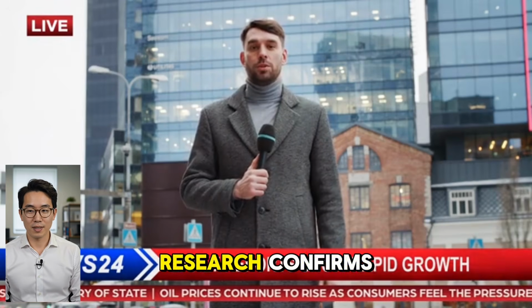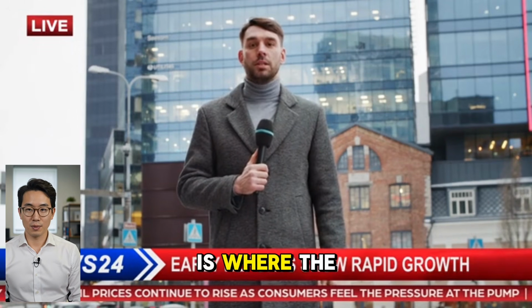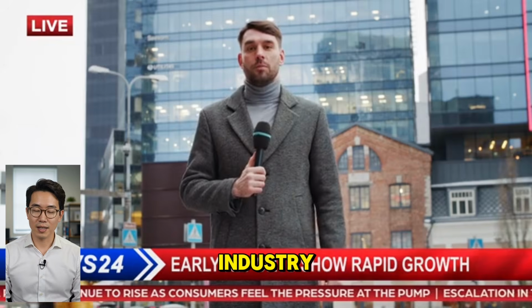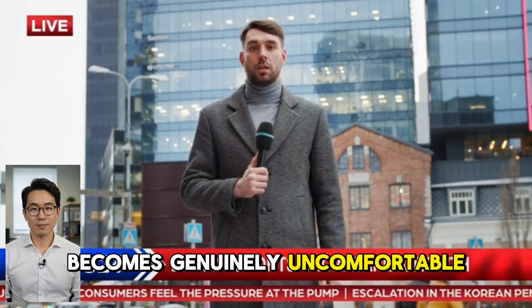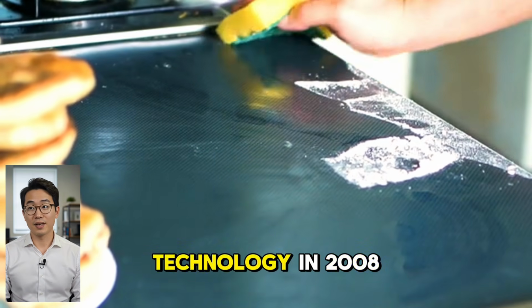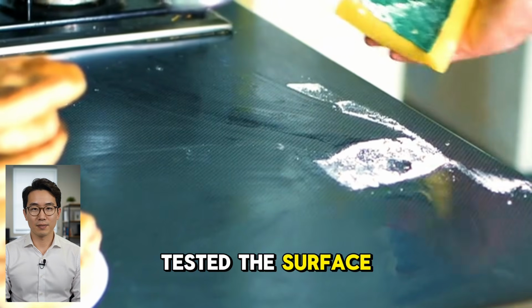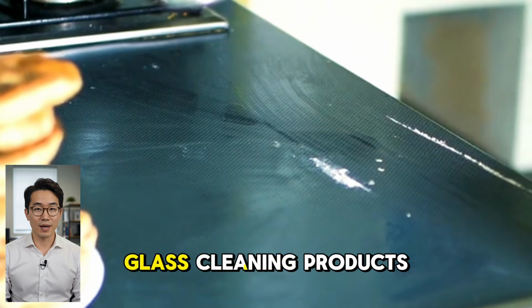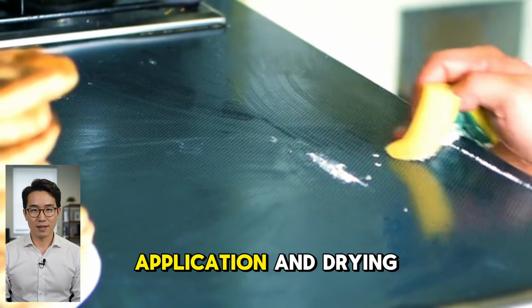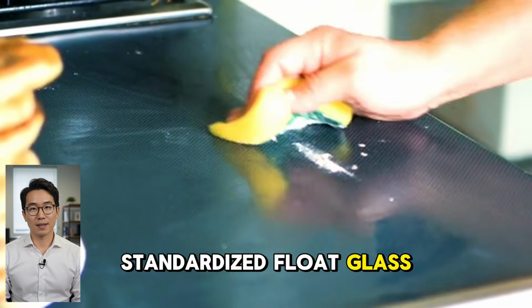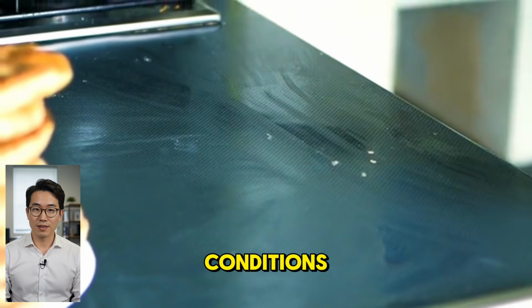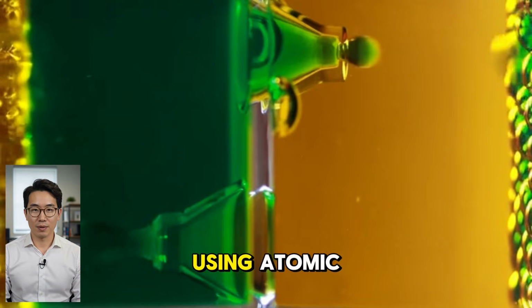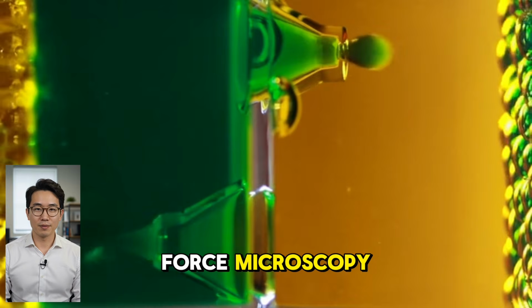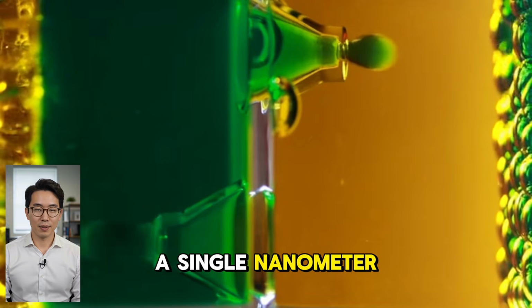Now let me show you what research confirms, because this is where the commercial glass cleaning product industry becomes genuinely uncomfortable. A study published in the Journal of Coatings Technology in 2008 tested the surface residue left by 15 household glass cleaning products after application and drying on standardized float glass panels under controlled laboratory conditions. Residue thickness was measured using atomic force microscopy, which can detect films as thin as a single nanometer.